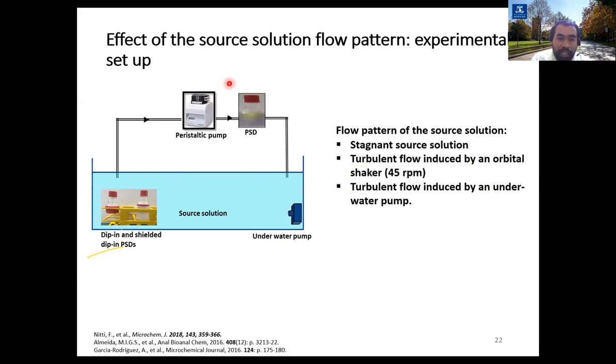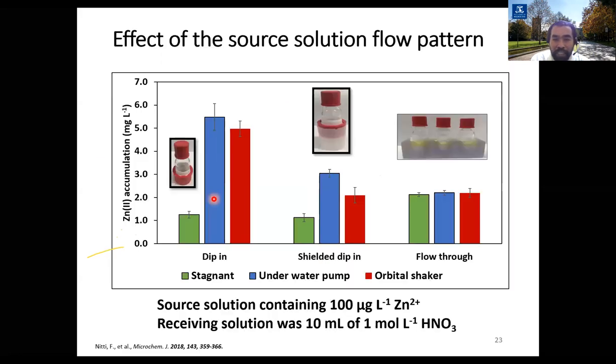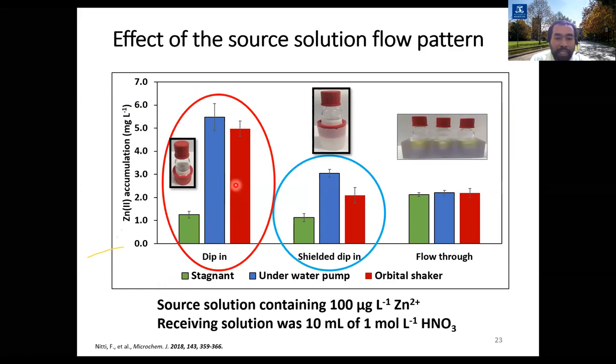We then study the amount of zinc accumulated in these three different passive sampling devices over 5 days. And this slide here shows the total amount of zinc accumulated after 5 days. So what basically happened is in the two cases, what you can see here is the accumulation from the three different conditions. The green one shows the case in stagnant water, blue one is the flow pattern induced by an underwater pump, while the red one shows the results from the flow pattern condition induced using an orbital shaker.